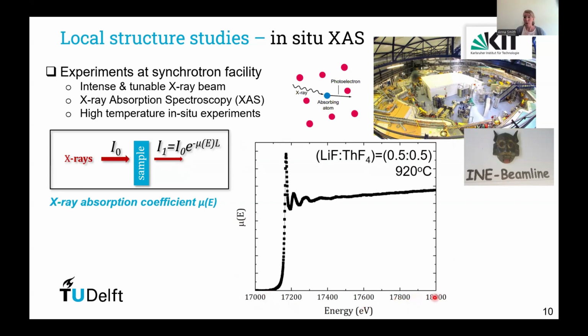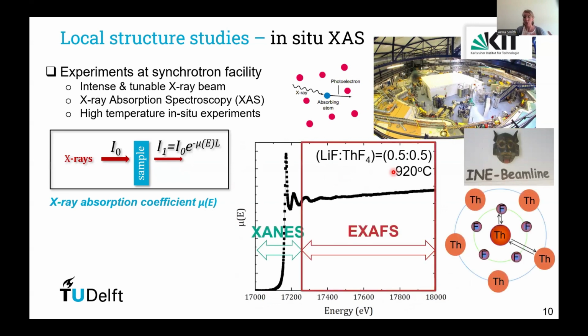What you see on this figure is an example of a measurement we did on a lithium fluoride, thorium fluoride mixture at 920 degrees Celsius. And in this kind of measurements, there are two regions of interest, the low energy region called the XANES and the high energy region called the EXAFS. It is this EXAFS that is mostly interesting in this case. It gives us some information on the local structure around, in this example, a thorium absorbing atom. So we get information on the first coordination shell, the fluorine around the thorium, and maybe also the second coordination shell.